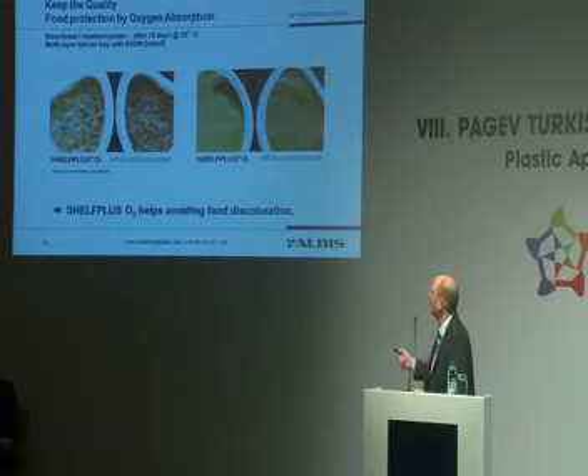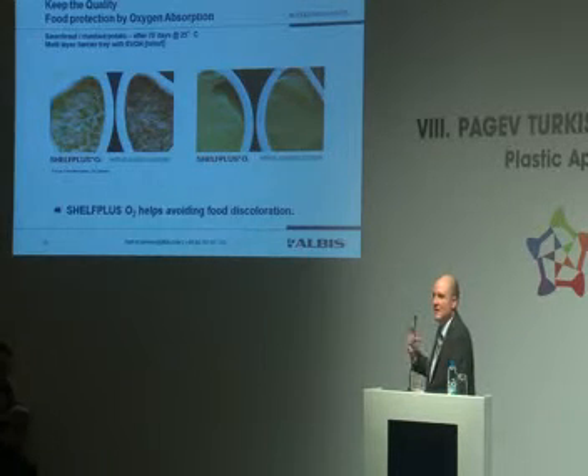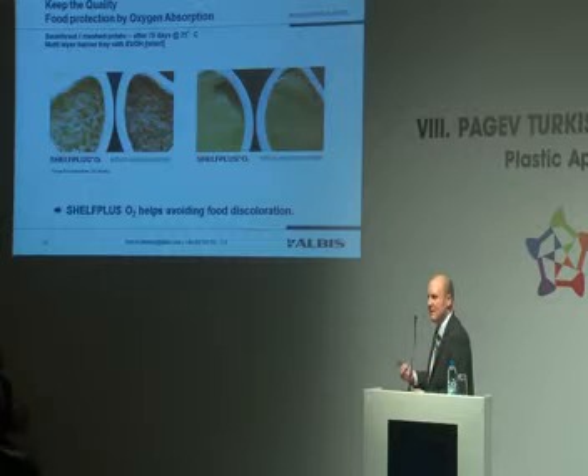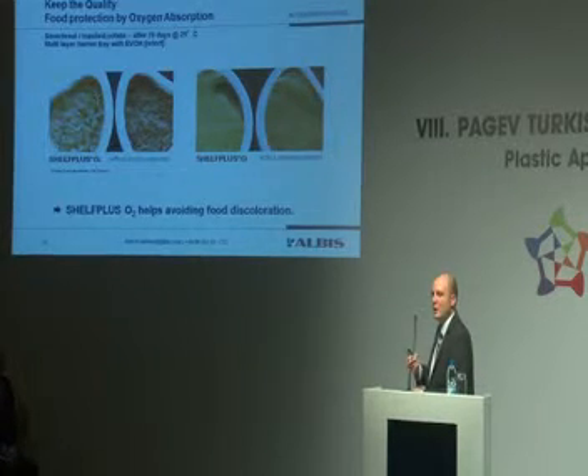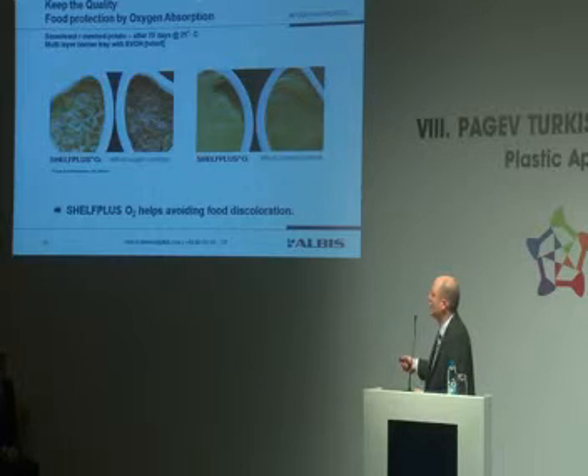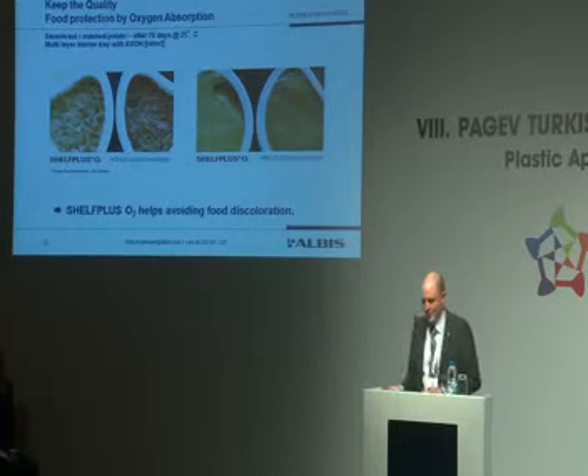And after that, they were stored 70 days at room temperature, a little bit above room temperature. Left-hand side pictures contain EVOH plus an oxygen scavenger. The right-hand side pictures contain only the EVOH barrier material. And you can see here, with the vegetables especially, a discoloration. This product is not bad. It still is within the shelf life. It is still good. You can still eat it. But what would you like to eat more after my presentation at lunch? This one or that one? And the same is also possible with the mashed potatoes.